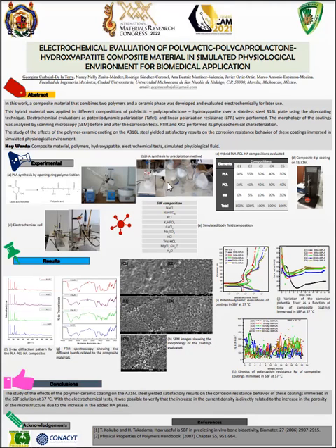The polycaprolactone was purchased from Sigma Laboratories. For the project, several compositions of the hybrid material were made as we can identify in Figure C. The solvent tetrahydrofuran was used to mix the materials. The coating of the stainless steel samples was carried out by immersion, by the dip coating technique. There is a photograph of the equipment we used to do the immersions.